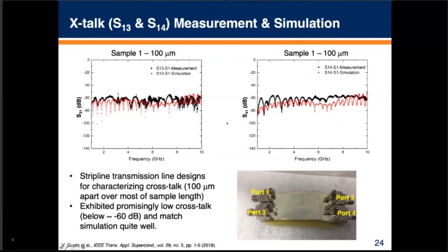But in these structures, we found that we're below 60 dB of crosstalk. There's simulation and measurement shown here. S13 is the near end crosstalk, and S14 is the far end crosstalk. You can see both of those are somewhere in the ballpark of the simulation that we did for this structure as well. So, nice low crosstalk structures.